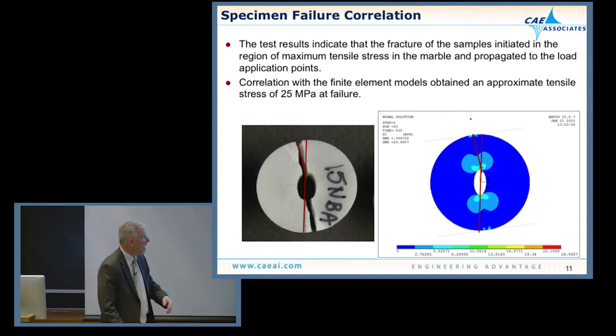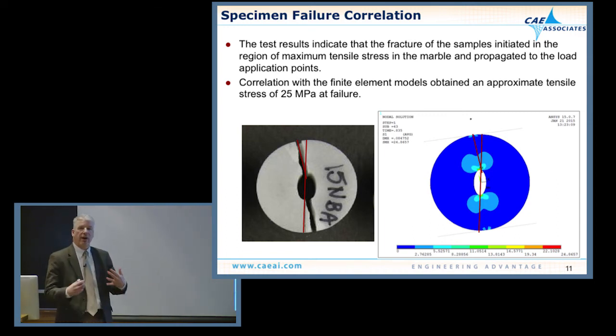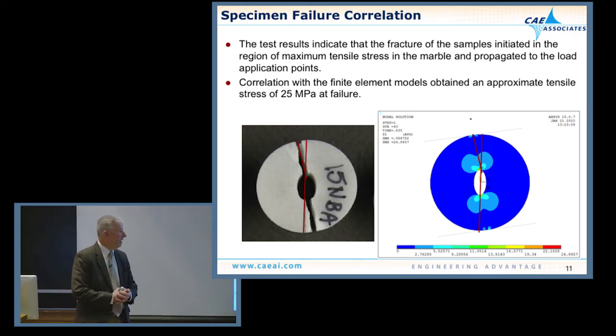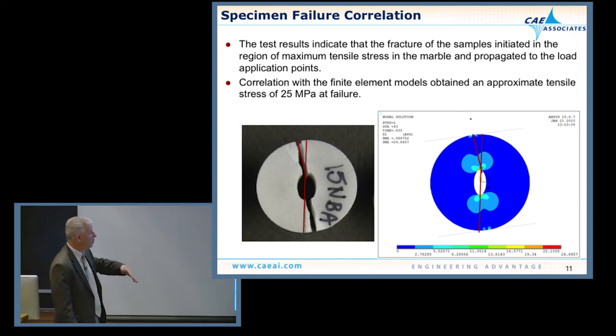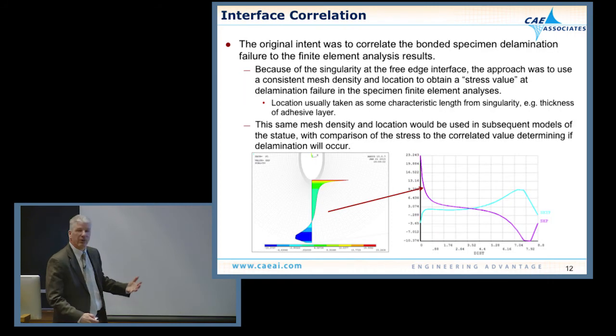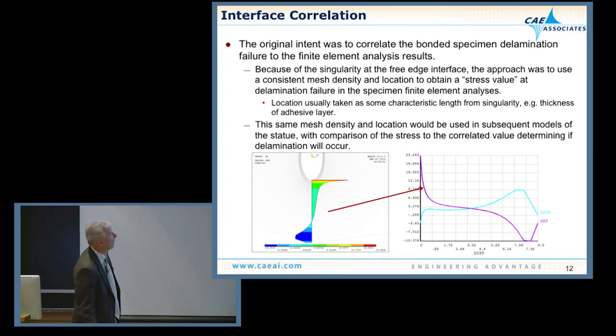We did that. And again, when we looked up Carrara marble, we found that there's a wide range of modulus and stiffness for that material. So by using these test specimens, we were able to basically come up with a very accurate account of what the stiffness would be.